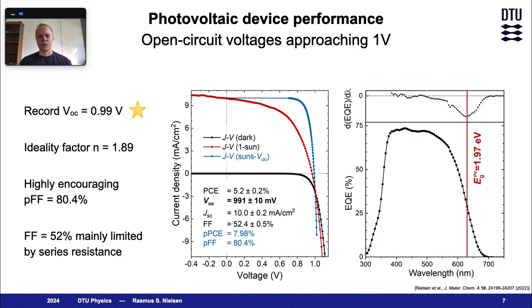If we study the photovoltaic device performance, we actually achieved a record open circuit voltage close to 1 volt. Now, to properly deconvolute transport losses from other non-idealities, we complemented our current voltage measurements with Suns-VOC, revealing an ideality factor of 1.89 and a highly encouraging pseudo-fill factor of more than 80%. This result tells us that the relatively low fill factor is mainly limited by parasitic series resistance.